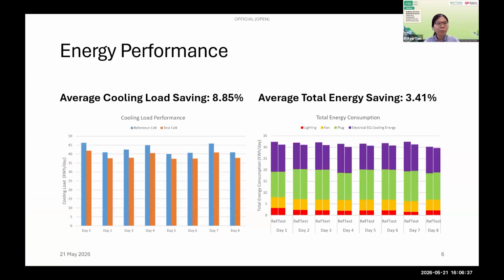Now for the energy performance. Across the test period of 8 days, the coated glazing delivered an average daily cooling load saving of 8.85%. And when you look at total energy, which includes lighting, fans, and plug loads, as well as cooling, the saving is 3.41%. This means that for a building owner, this translates directly into lower utility bills and a lower carbon footprint.